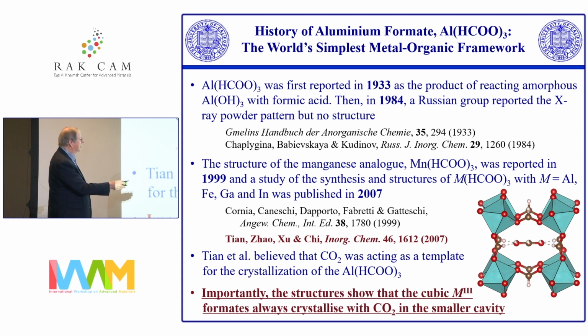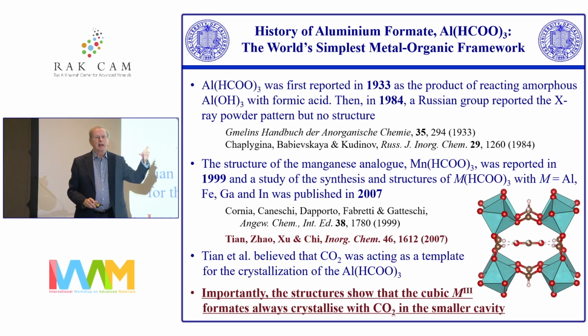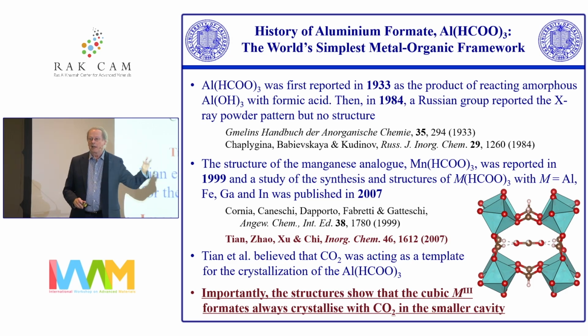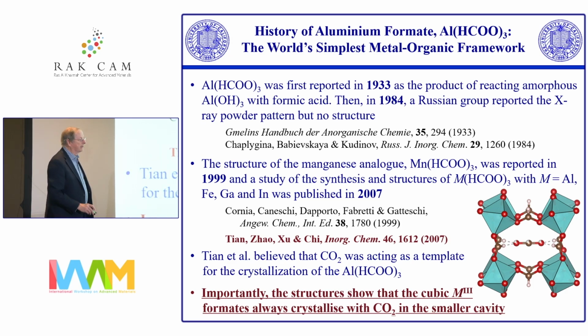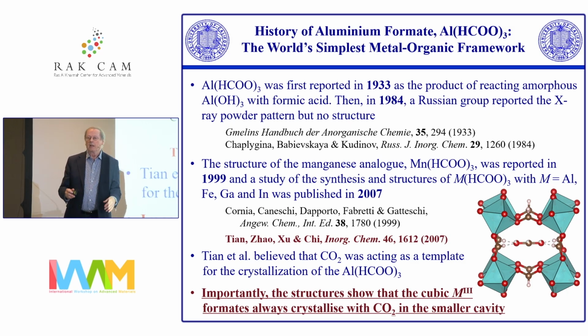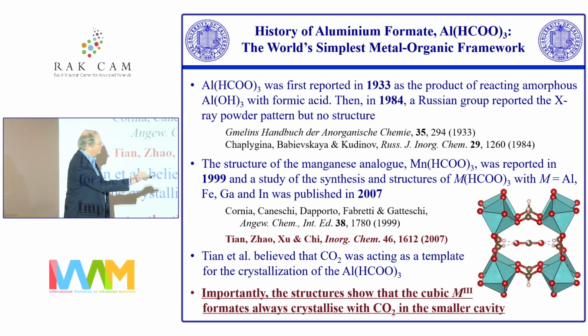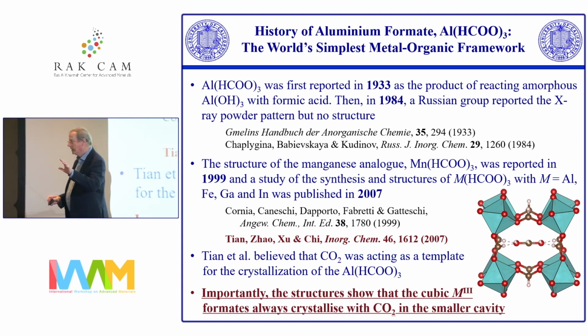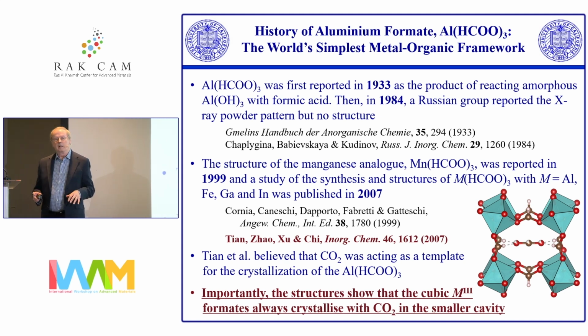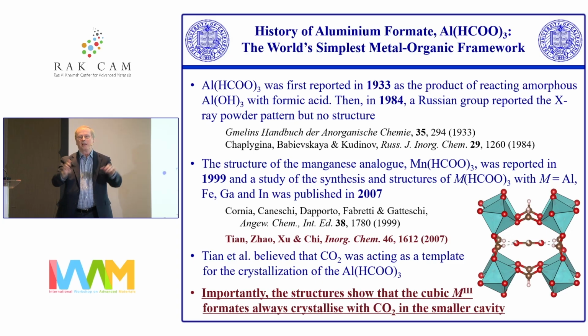But then about 8 years later, a Chinese group wrote a very nice paper in Inorganic Chemistry, and they looked at the aluminum analog, the gallium analog, the iron analog, and the indium analog, and they published crystal structures for all of them, and they've all got CO2 in the cavity, just like you see over here. Here's the CO2 in this kind of ReO3 cavity, neutral CO2. So this was kind of hiding in the open, as it were. Nobody really thought very much about it.